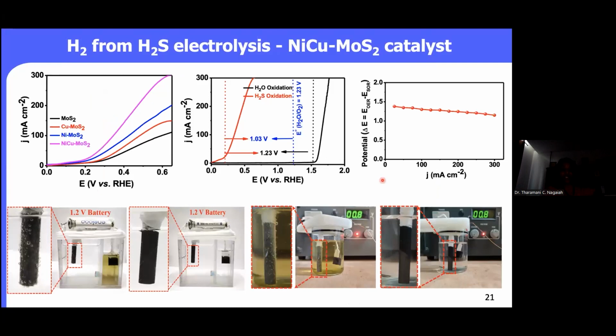So now the question is to understand the H2S electrolysis. We have performed the experiment under similar conditions, similar to the electrochemical water splitting. The only thing is we are purging the solution with H2S for almost 3 hours. And we have done some control experiments to understand the catalytic ability of the proposed catalyst here. You can see that there is an increase in the oxidation current at 0.2 volt. And we are speculating that this is due to the sulfur oxidation reaction.